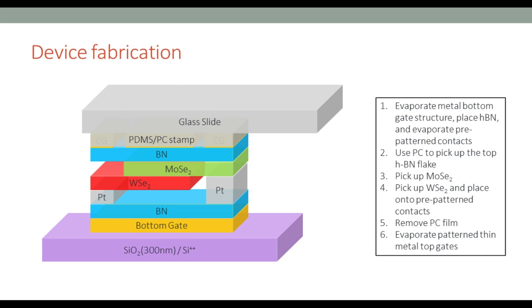And then we evaporate gates. These gates are very important because they are what actually allow us to control the doping or electric field that the excitons feel. And CG here is contact gate, which allows us to actually make ohmic contacts to the materials.